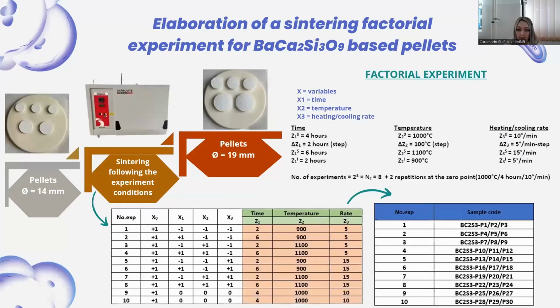the sintering process. In order to obtain the optimal condition for the sintering, we elaborated a sintering factorial experiment, starting from 3 variables: time, temperature, and heating or cooling rate. And we started from a 0 point using the data that we found in the literature: 1000 Celsius degrees for 4 hours with a heating rate of 10 Celsius degrees per minute. And for each of these variables, we set one step.